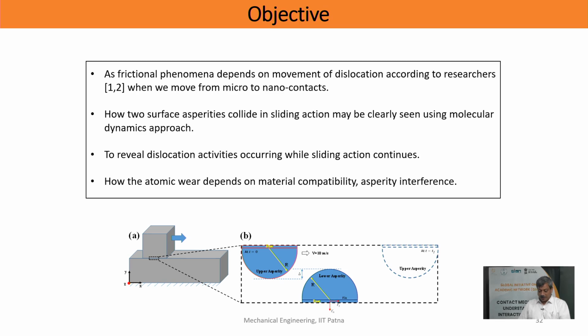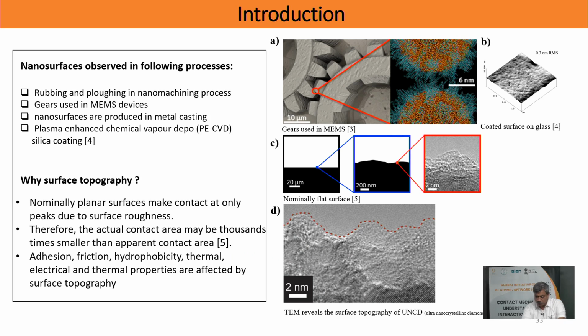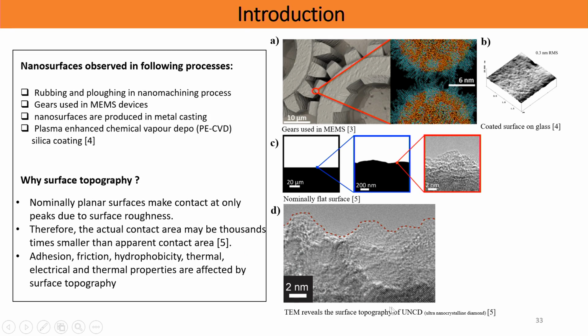That is coming out here. Also, we've tried to correlate the basic laws which we use at macro scale and done a plot, which I'll just show you at the end, which is like Hertz's law and Archard's wear law. At this scale, at the nano scale, how it follows, whether it is valid or not. So there is some indication to that also. So we know that these are, we've taken this from a reference, by the way, for UNCD, ultra nanocrystalline diamond, if you see the surface here at 2 nanometer scale, then you are able to see the surface roughness, which is not very different from the surface roughness you see in macro scale or micro scale also. Okay.